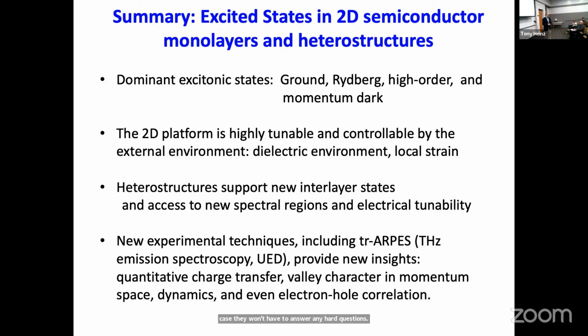Bill. So early on at the talk, you told us, well, the spectra of the exciton is not hydrogenic because there's this dielectric screening. Okay. So you talked about the spectra not being hydrogenic because of the screening, and then later you showed us this picture about how when you went to higher states, then more of the field that one imagines is between the electron and the hole is outside the dielectric. So what I'm wondering is, if you go to higher and higher states, does it return to being hydrogenic? That is, does it look like a Rydberg spectrum with a big quantum defect, or something else going on?